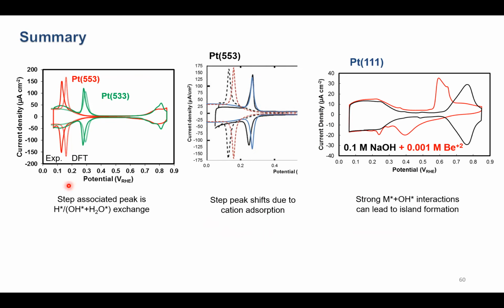And so I'll conclude just by summarizing. Hopefully I've convinced you we've shown that these step-associated peaks on platinum measured in electrochemistry correspond not to hydrogen adsorption, but an exchange between adsorbed hydrogen and adsorbed hydroxide in water, that they shift to more positive potentials with increasing pH due to the adsorption of a cation, which weakens OH and water adsorption on the step. And in some cases, we actually see such strong cation hydroxide interactions that they lead to island formation on the surface.